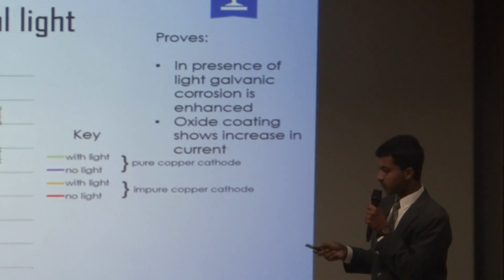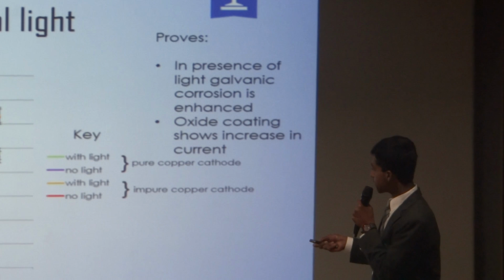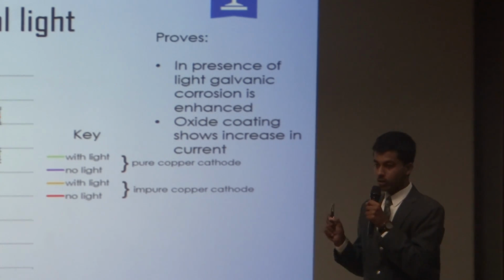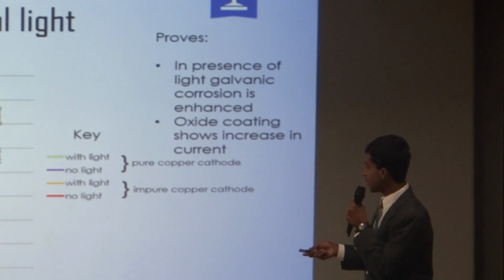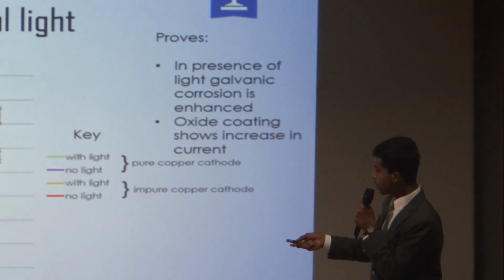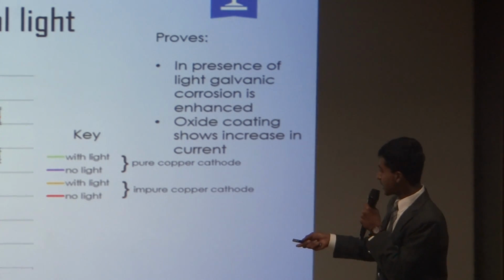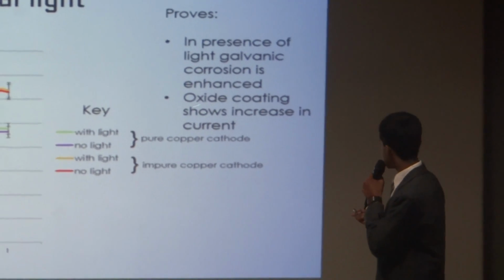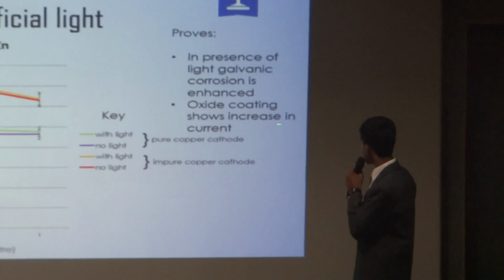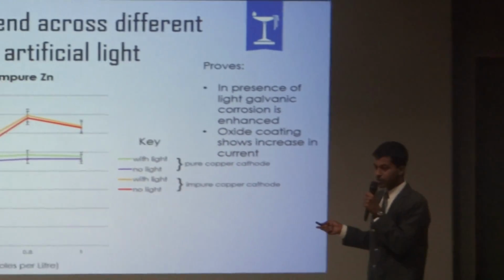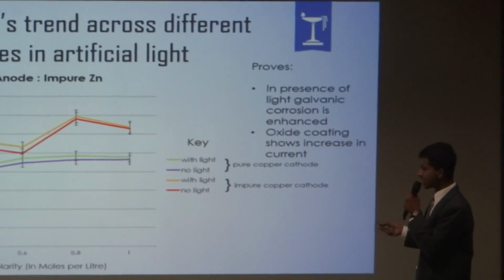Also another observation which we noted was that this combination, which was coated with an oxide layer on it, showed as a whole more readings on an average than the combination which was pure. So we also came up with this, that oxide coating shows increase in current. Now as to the first observation which we noted was that